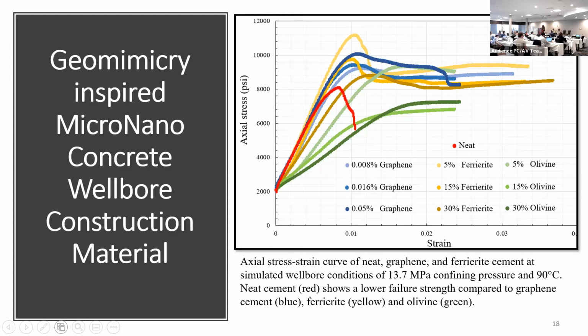Zeolite, for example, has this mesostructure. It takes some of that cement pore water. If you add it in the right amount, up to 5%, it removes the excessive water that is needed for rheological pumping down of cement but actually causes microporosity. So that could help shift everything into the nanoporosity range. Later on, if you have a fracture and you need extra aqueous chemistry to heal it, the zeolite will release that water and you end up forming bridging elements in the fractures.